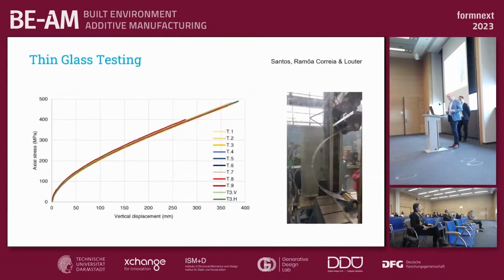Here you can see a plot of it. We reach strength values of well over 400 megapascals, and actually in this setup it failed from the clamp, so we could push it much further, but we had to improve the setup for that, and then you can get to 800 or 900 megapascals, which is, let's say, in the range of high strength steels.